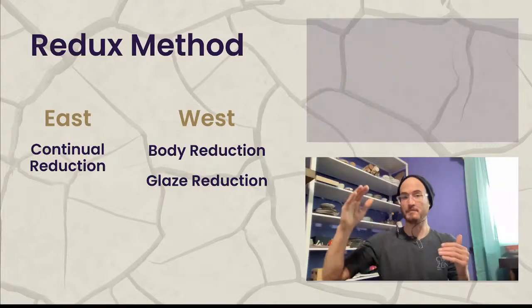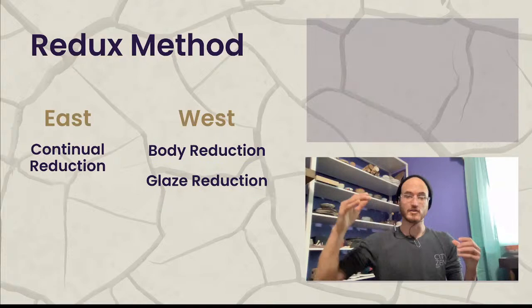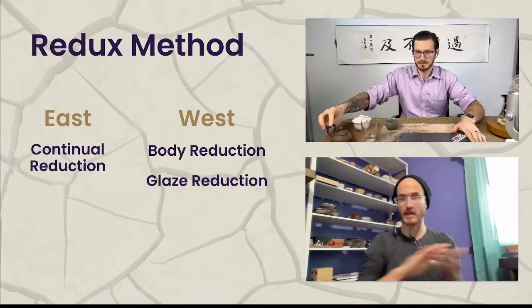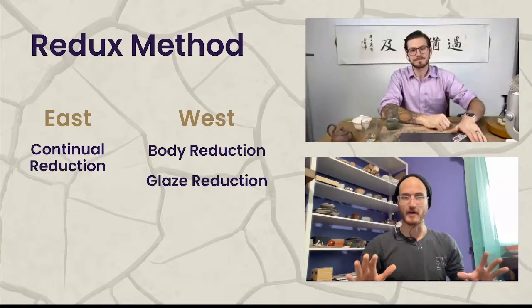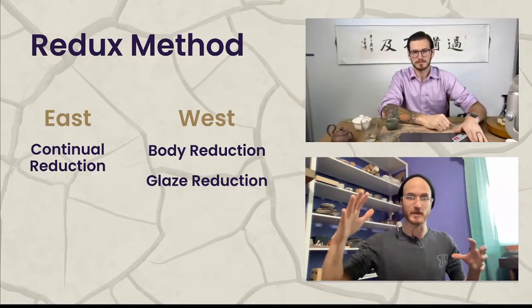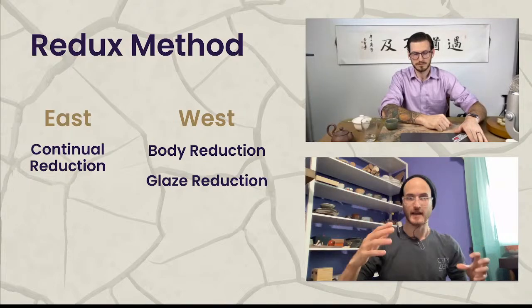There are different stylistic things that you can do as well. Oftentimes in wood kilns, you'll do what's called a reduction cool. And that means that you're loading the whole firebox full of wood so that there's way too much wood that can possibly be efficiently combusted, but it's causing a really heavy reduction at the very end of the firing. And this is like, my hands are showing the flame going through the kiln. So you get a really heavy reduction firing going through, and that drops the temperature drastically compared to if you were trying to climb, but it actually makes it so that it goes more slowly down than if you had just clammed everything up and stopped the firing. So it basically allows you to reduce while cooling the kiln slower and controlled, sort of that descent.